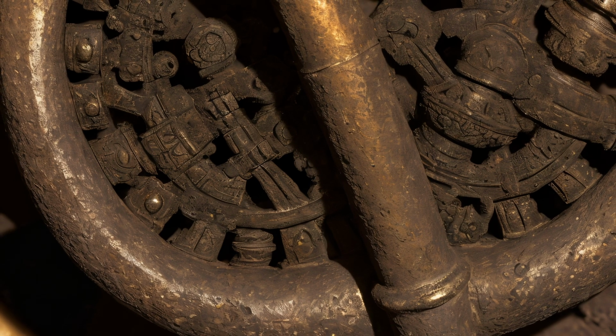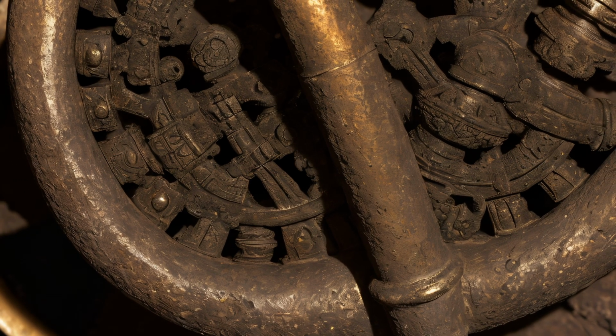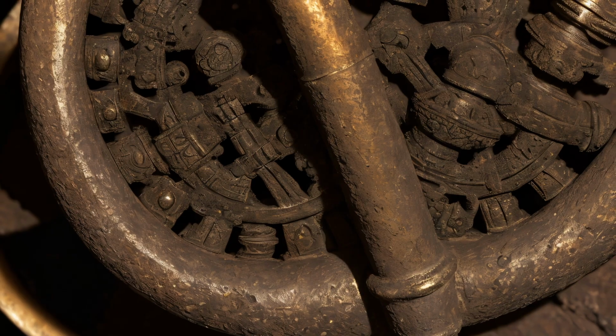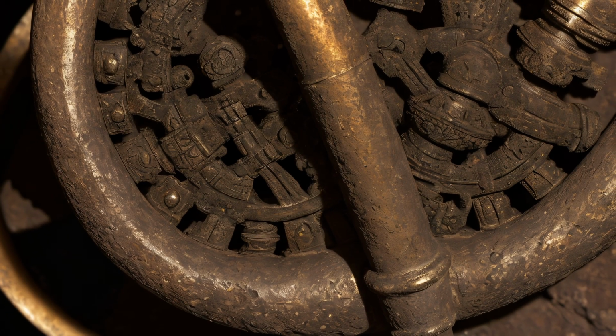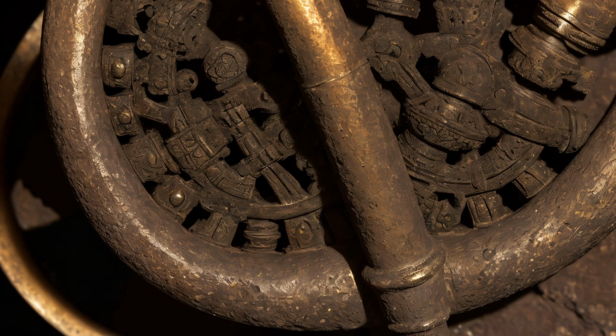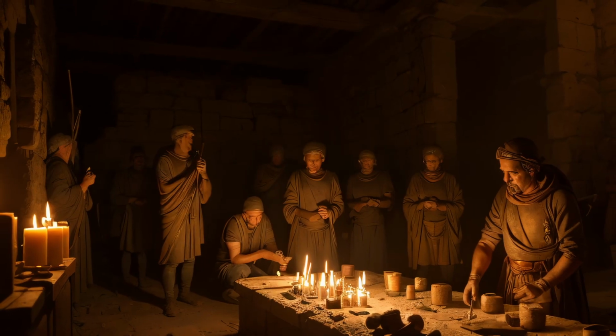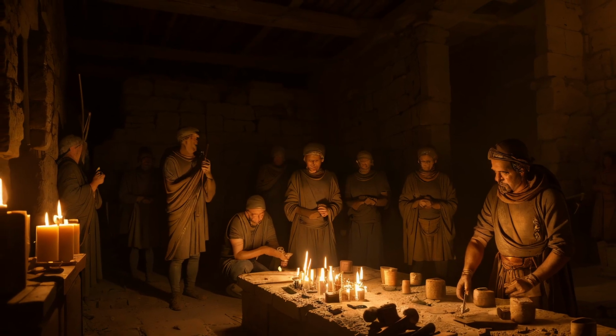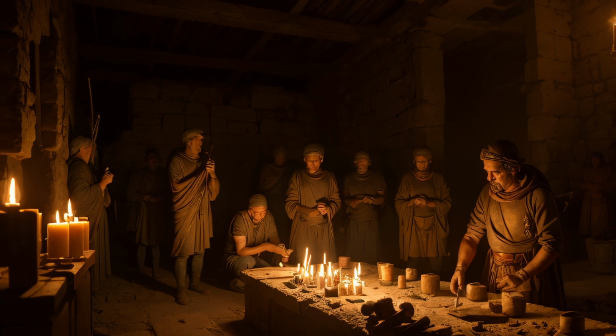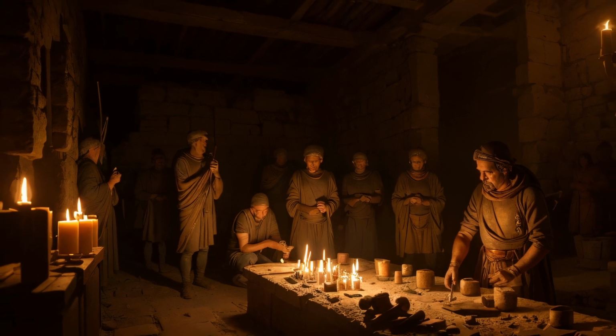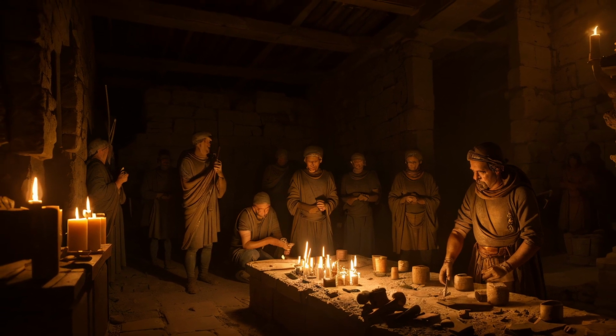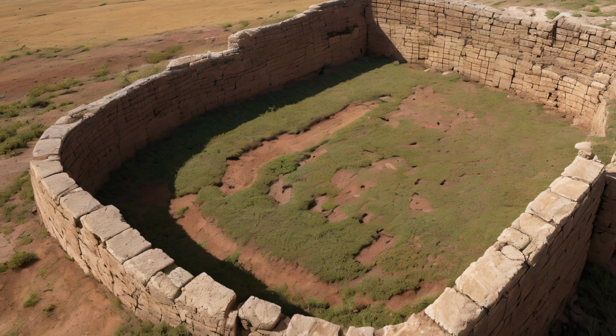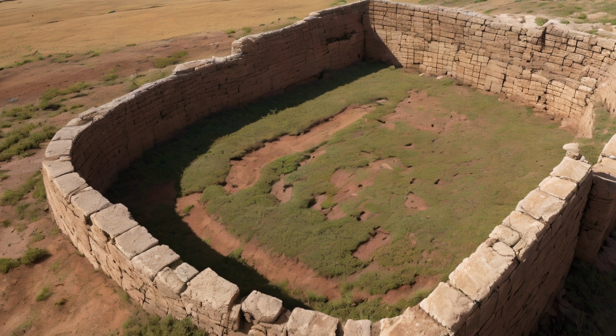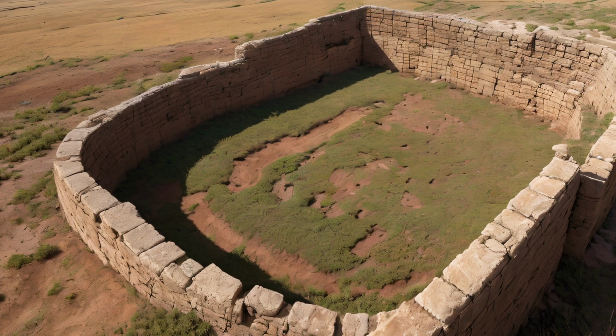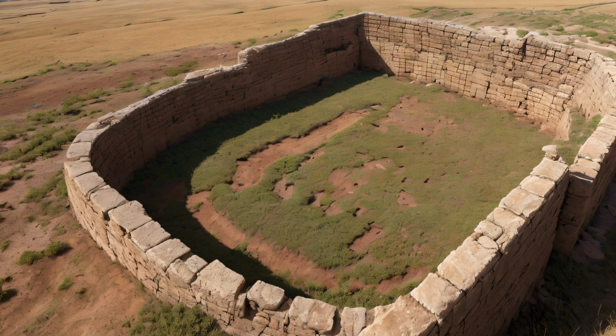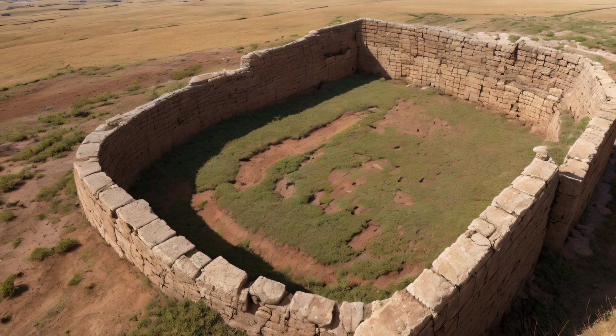Bronze's role in ancient acoustic engineering was not incidental but meticulously calculated, rooted in its unique metallurgical composition and physical attributes. Archaeological analyses of surviving artifacts from the Hellenistic period reveal that bronze typically contained between 10% to 20% tin, with the remainder copper. This specific ratio optimized the alloy's tensile strength while maintaining a degree of malleability essential for crafting hollow tubes. The density of bronze, approximately 8.8 g/cm³, enabled it to act as an effective medium for